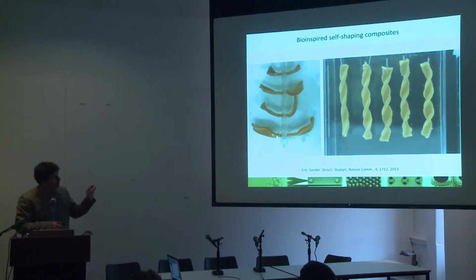And what's really important here is that, of course, you do have synthetic materials that are also shape-changing, like metallic alloys and other polymers. But again, these are specific to a narrow selection of materials. If you think of metallic alloys, you have, for example, nickel titanium, which has one specific phase transformation at the atomic level that allows for this shape memory effect. And with polymers, the same thing. You always need polymers with a specific glass transition temperature. And here, you're not limited at all. You can use any type of fiber, which is sustainable, energy efficient, bioresorbable, and so on, and any type of matrix as long as it's responsive to an external stimulus.